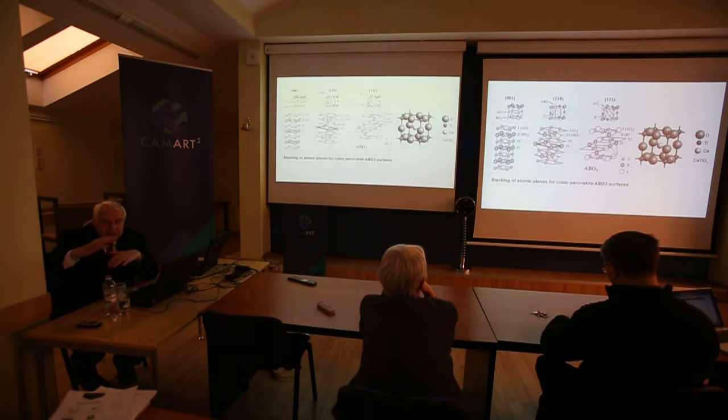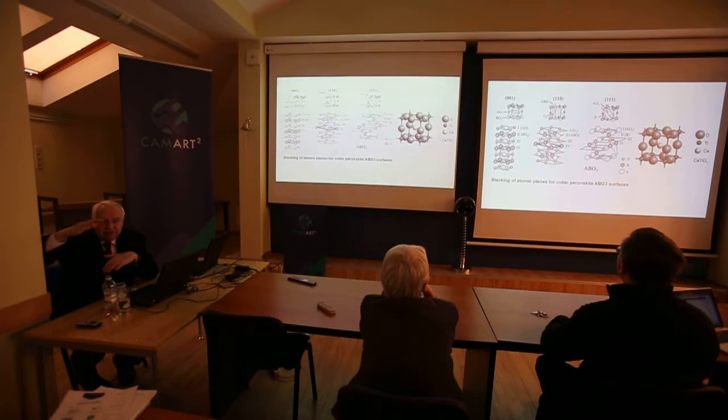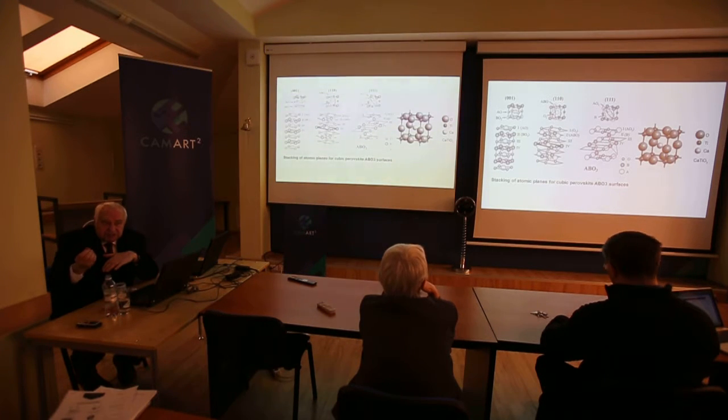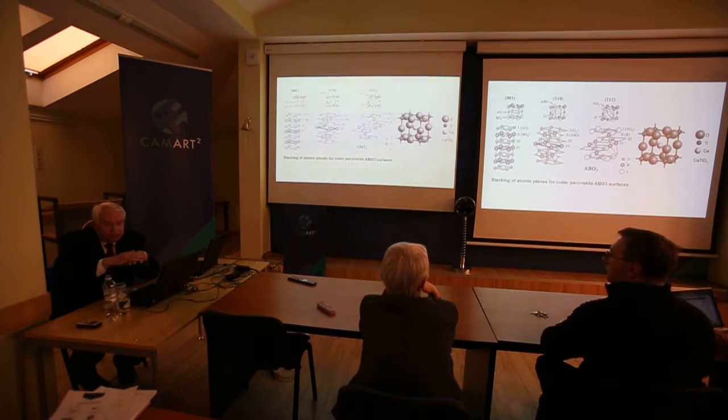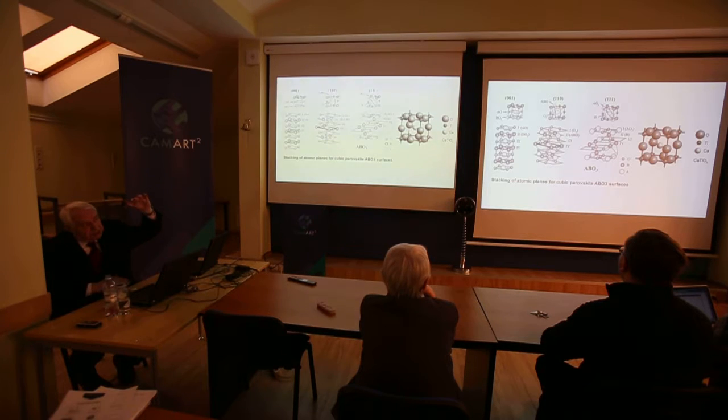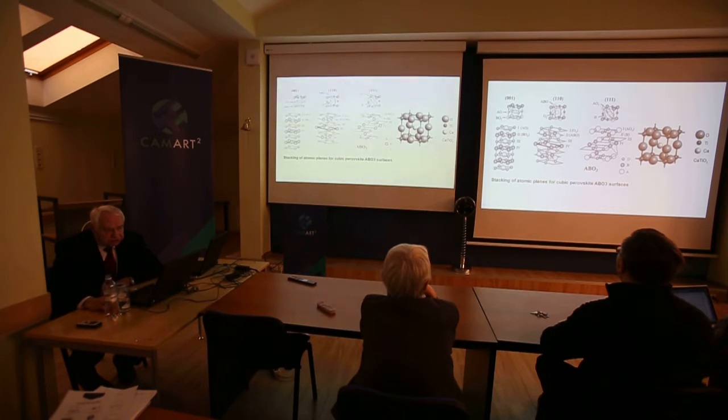The slab is huge. Your possibilities on computers are not very powerful. So you need to investigate the convergence of the results when you increase the thickness of this slab. And what is the criterion? You take the central plane, but the central plane you can find only for an odd number of planes, and see when, for example, the charge distribution on central planes is stabilized. So it means that adding the next outer planes will not change anything. Therefore, the first model is this one, without dipole moment.